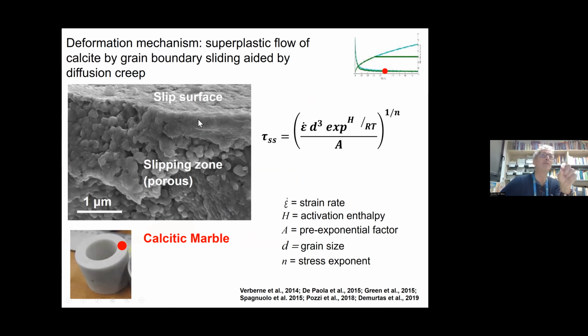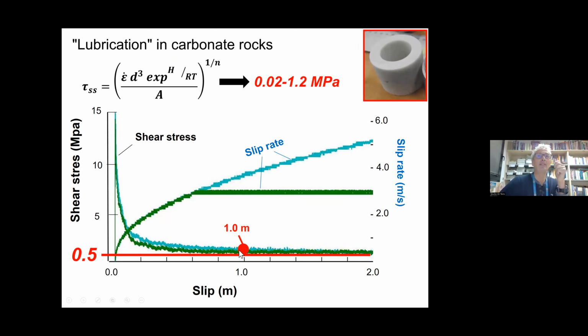So velocity of sliding for a given thickness of tens of microns or 50 microns. Then you need grain size, stuff like that, but especially temperature. Well, if you put in these values, you can really fit this very, very low shear stress, if the temperature is high enough, which is something we measure, and if the grain size, which you will measure at the end of the experiment. Well, and there is an activation energy. These are crystal plastic processes, so you need some activation energy and so on. However, you can really fit the experimental observations. So there is both textural evidence, but also this estimate that fits somehow. So depending on the rock type, you can have frictional melts, or you can have this kind of process going on, maybe.